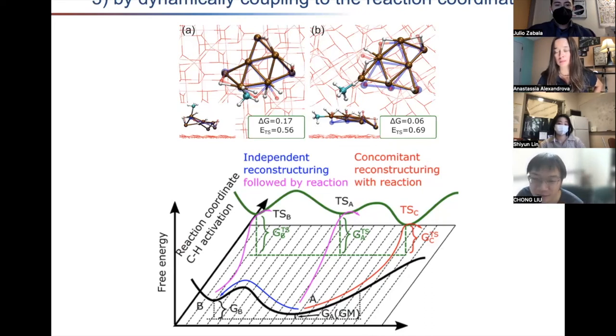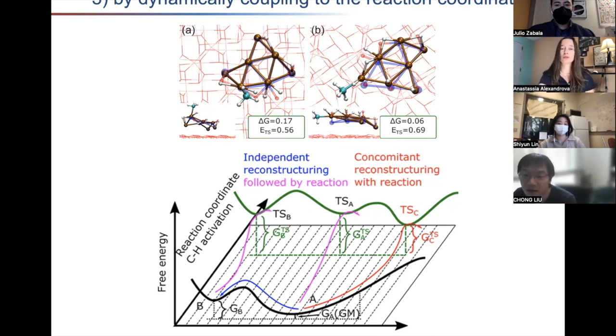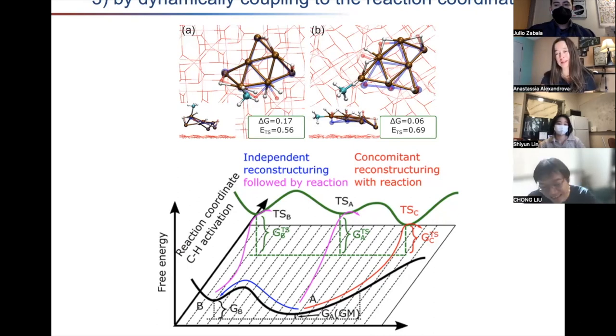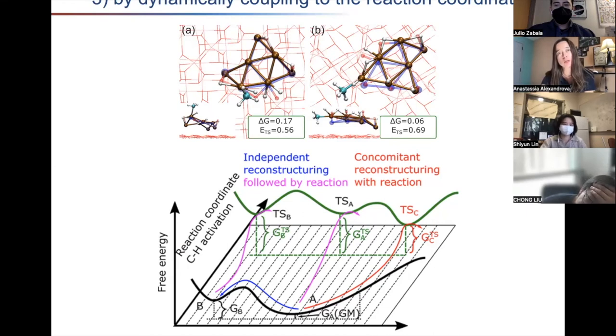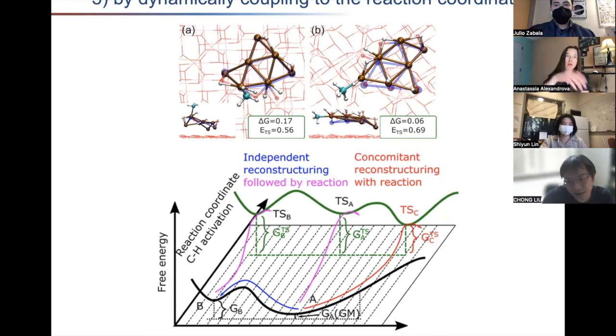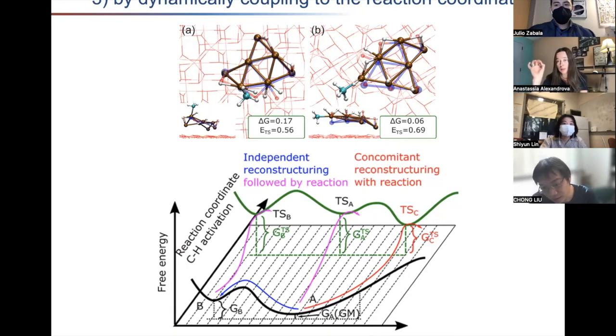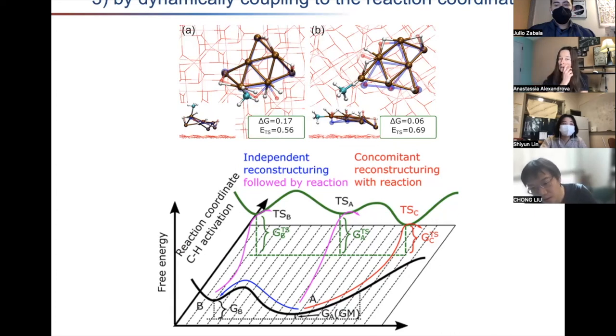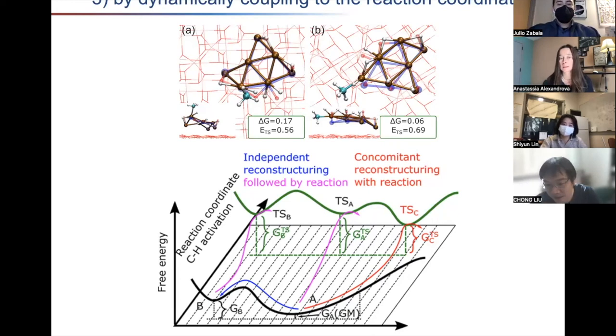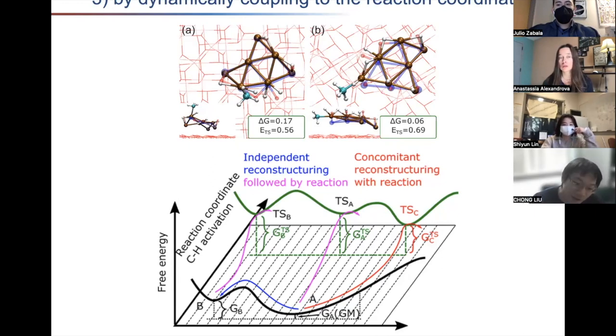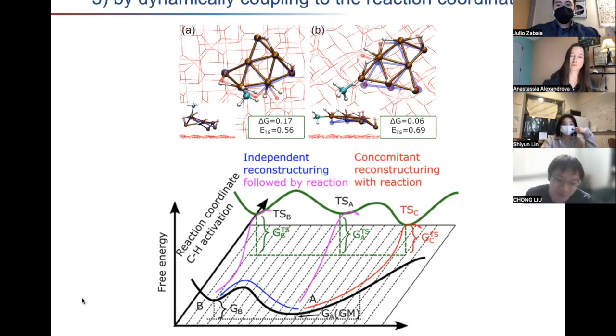Chong: I usually try to have a timescale in mind — how fast does the thermal bath need to be to ensure equilibration? Based on your simulations, does it mean hundreds of picoseconds are sufficient enough? Yes, picoseconds are sufficient. We are now also developing master-equation-type approaches where we want to see if there are minima either inaccessible because separated by large barriers, or separated by such shallow barriers they have no lifetime — in which case our Boltzmann picture would have to be modified to exclude some things or overpopulate others.